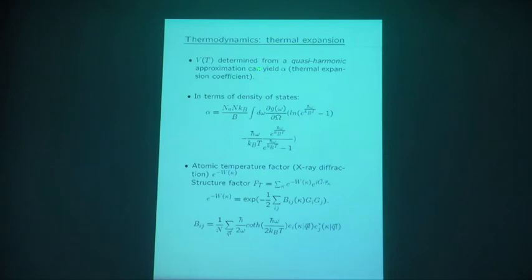So V of T is determined using quasi-harmonic approximation, and this alpha, the linear thermal expansion coefficient, is basically linked with the phonon density of states and this normal Bose-Einstein factor. Atomic temperature factors, basically, these are linked with X-ray diffraction, which are also measurable, the Debye-Waller factor. They are all related to phonons. Okay? So a lot of interesting temperature-dependent properties can be obtained using phonons in harmonic or quasi-harmonic